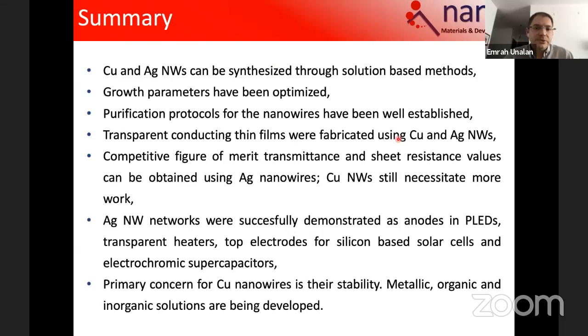And the summary slide is that I think we can control the synthesis of these nanowires. Now we can get gram quantities of these materials after optimizing the growth parameters. And we also optimized the purification protocols. So we are getting figure of merit optoelectronic performance compared to ITO. So I think it's a rival now. And there were some problems of environmental, mechanical, and chemical stability issues. And I think we also have solutions to solve them for both silver and copper.